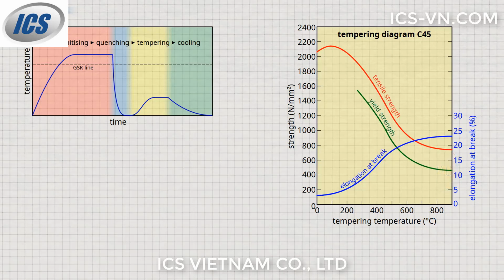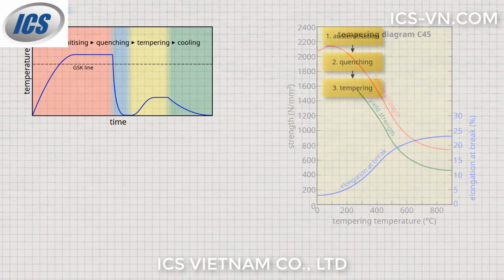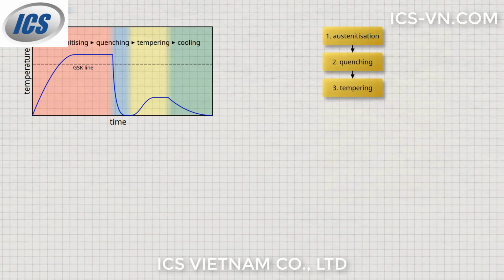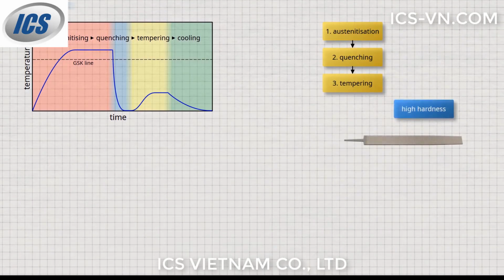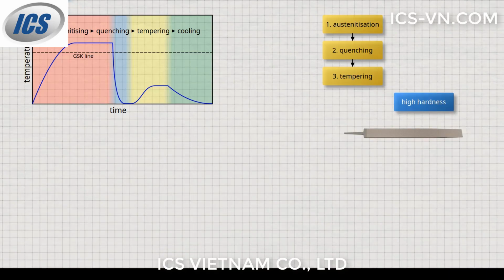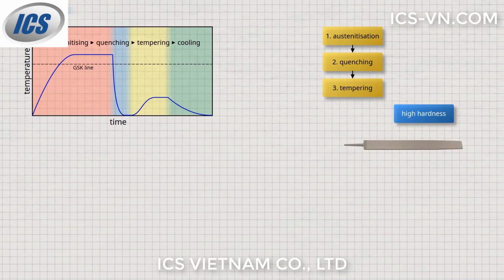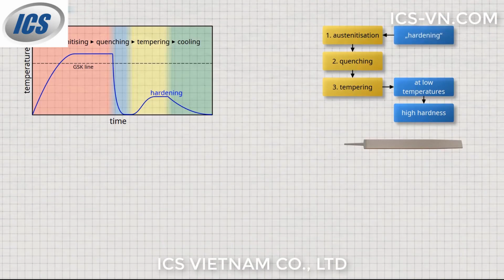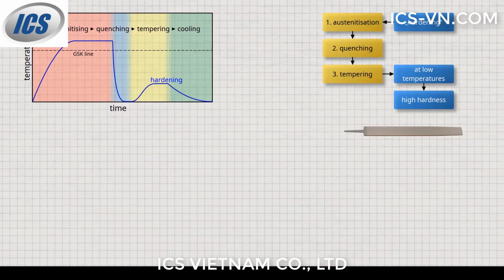Thus, there are basically two different ways of controlling the process, depending on the material property to be achieved. If the steel is to be very hard and wear resistant, a high degree of hardness is required. The steel is therefore tempered at relatively low temperatures. This process is known as hardening, and the steel is then called hardened steel.